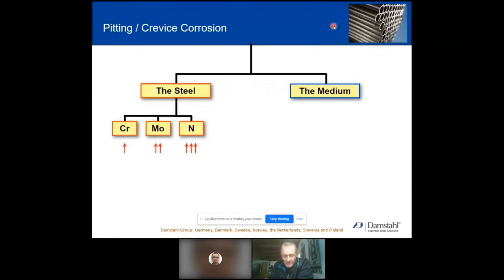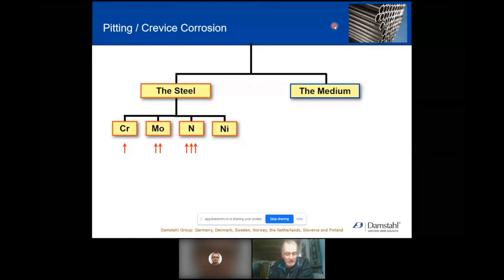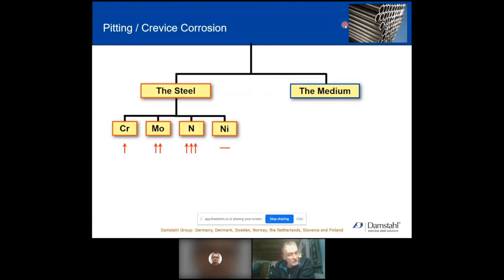The negative side of nitrogen is that we are only naturally able to dissolve somewhere between 0.2 and 0.3% nitrogen in the steel. But even 0.2% is actually quite effective. Nickel is very good for stabilizing the austenitic, the face-centered cubic structure. But when we're talking about initiation of pitting corrosion, it doesn't really matter.